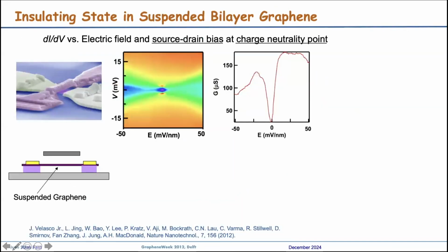And so what we do is we have this suspended graphene. This is before hBN was demonstrated by the Columbia group to be a really great substrate. This is how we make very, very clean samples. We suspend graphene. We have a backgate and we have a suspended topgate, which is like an air bridge. We current anneal the samples so that they're very clean near the charge neutrality point. And then this is a bias spectroscopy measurement. This plots two-terminal conductance, or differential dI/dV, versus electric field, which is the horizontal axis, and source drain bias, which is the vertical axis. This is done at charge neutrality point.